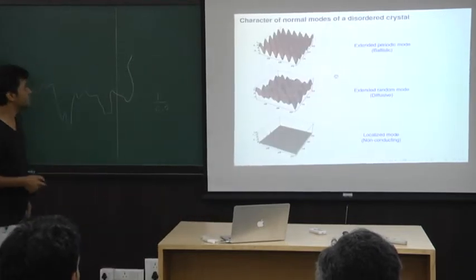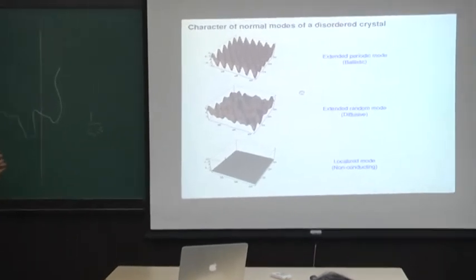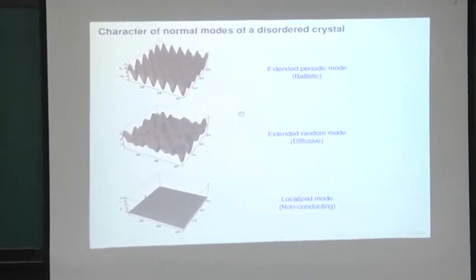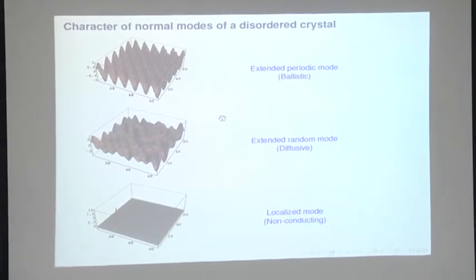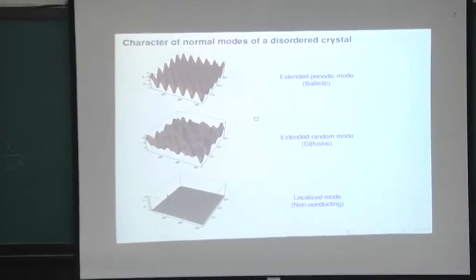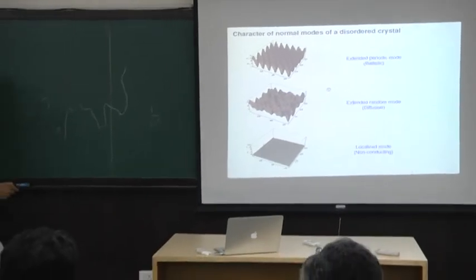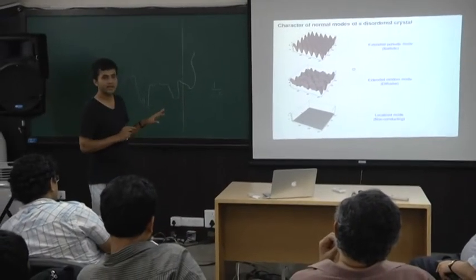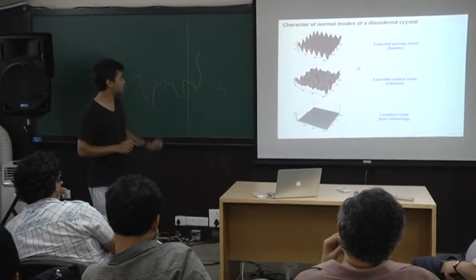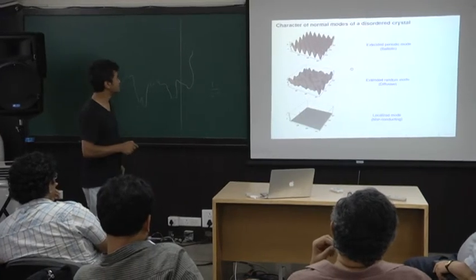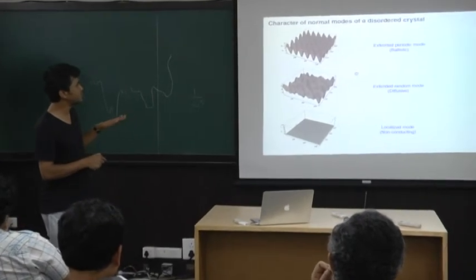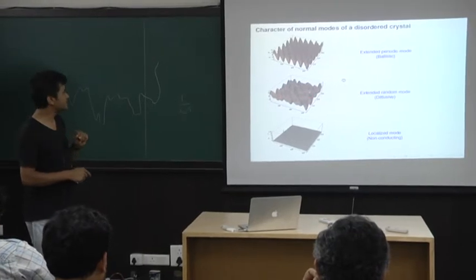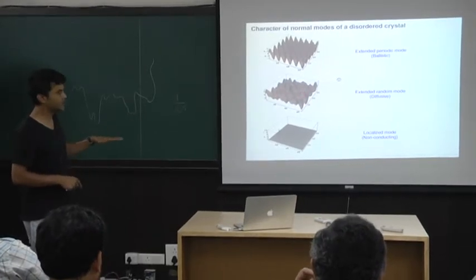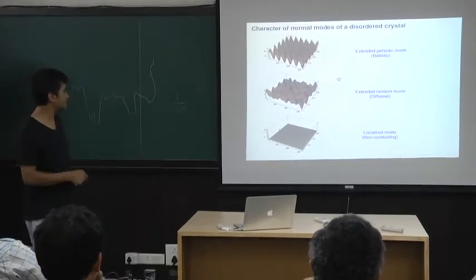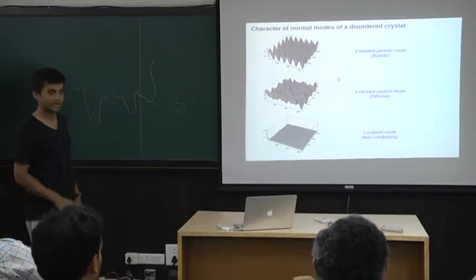So the thing I wanted to say is that you have diffusivity at each frequency. Supposing you just look at the eigenmodes at each frequency, then typically what you will find is that they look something like this. This is for the harmonic crystal that I had talked about, not about this system. In that system you will find that there are some modes which look like plane waves. There are some which I call diffusive, but they are kind of random but still extended, and then there are these localized modes. So these are the three kinds.